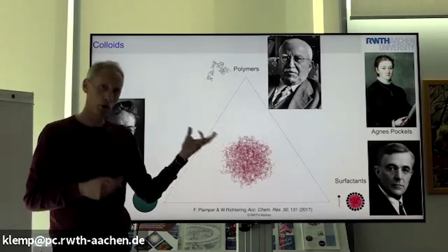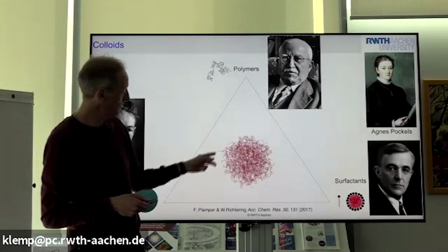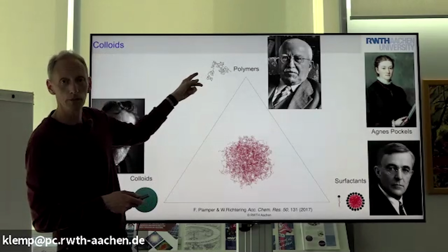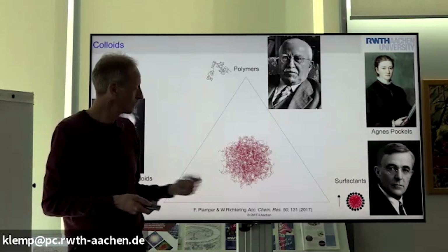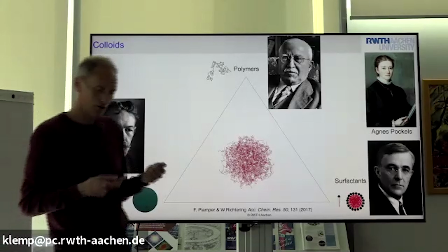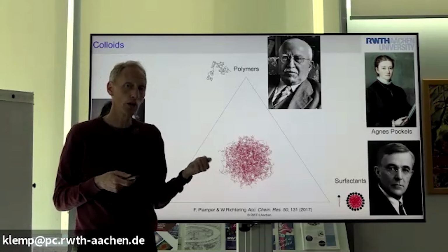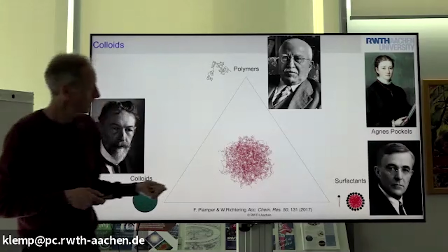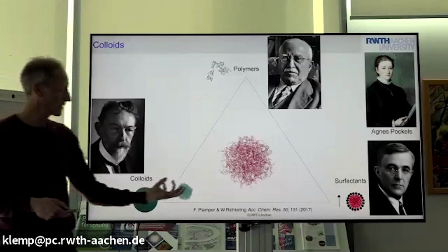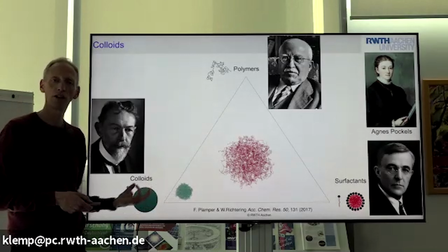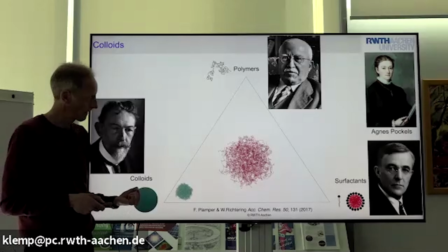They are swollen as a polymer network. So the surface is like a linear polymer. So it's cross-linked polymer. It's swollen in the solvent. And if we change the solvent conditions such that the solvent becomes a poor solvent, then this swollen network can collapse. And if they collapse, they basically become a latex. They become a regular rigid colloid.